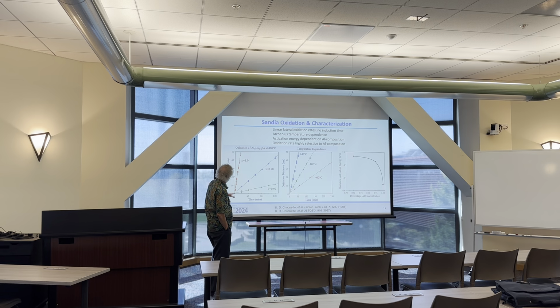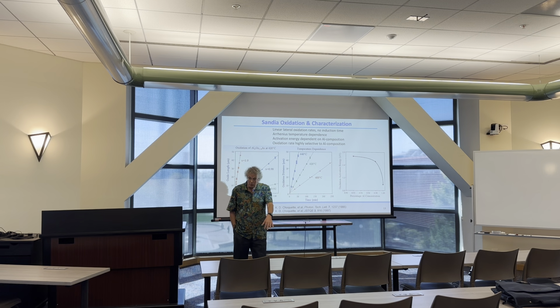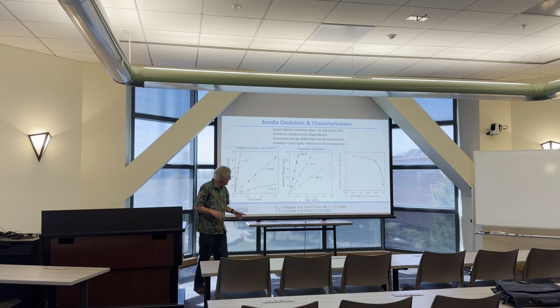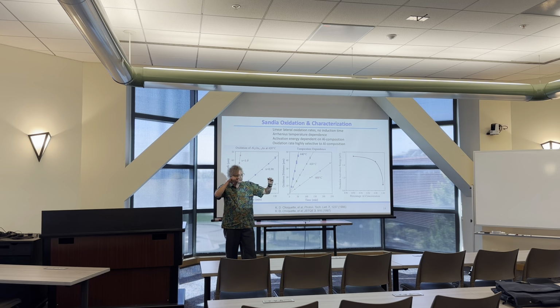So this is, again, we were looking at the oxidation rates of varying the composition. The key thing that was really interesting here is these are linear oxidation rates. If you go back to your 444 notes, you will realize that the oxidation of oxides is parabolic, and the only way that you get linear is because of the geometry of this structure, which is we're laterally oxidizing through layers that are confining the oxidation rate. So that gives you very linear rates with no induction period.